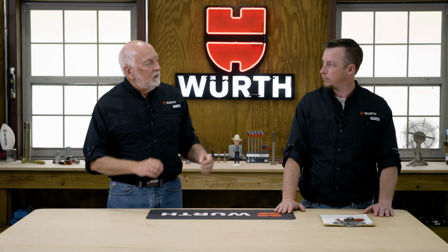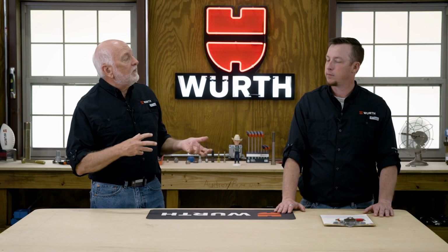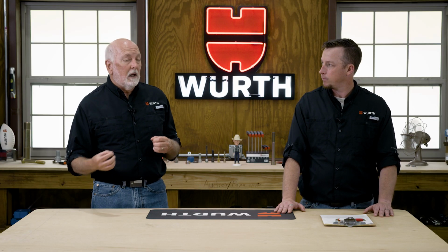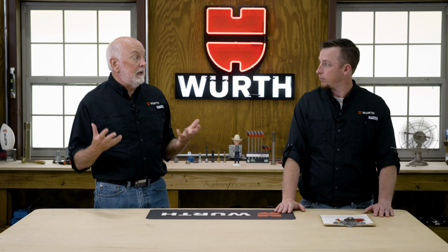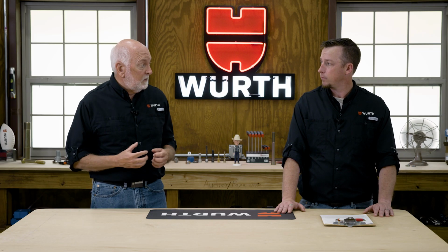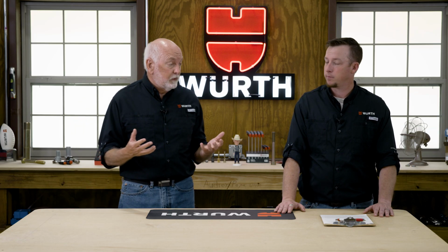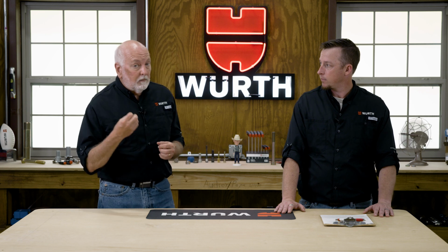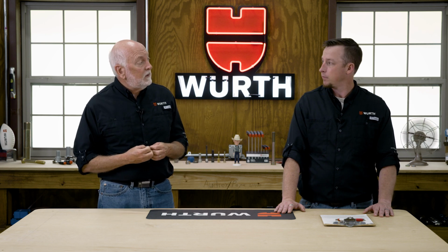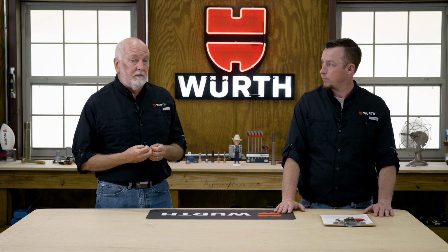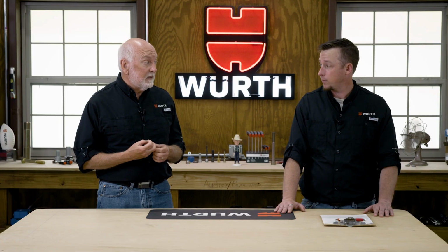So Aaron, with the finishes over 1,000-hour salt spray tests, a lot of customers are replacing stainless steel with zinc flake coatings. So that's a high corrosion resistance. And when you do that with steel parts in the coating, it's about a 30% cost savings. Wow. Pretty significant. Sure is. Zinc flake coatings, high corrosion resistance, competitive price. We're very excited about it in the fastener industry.